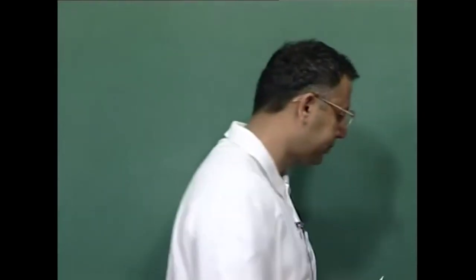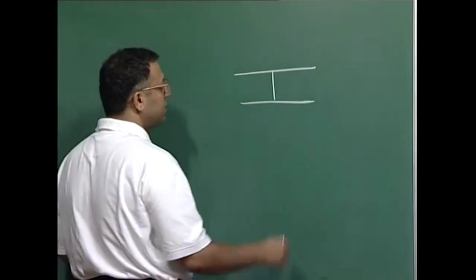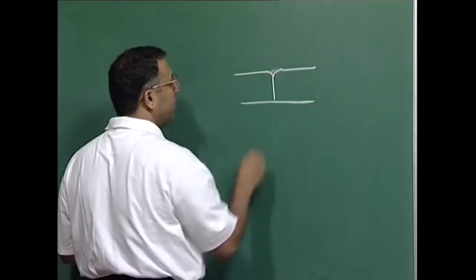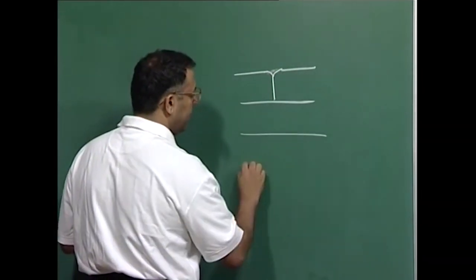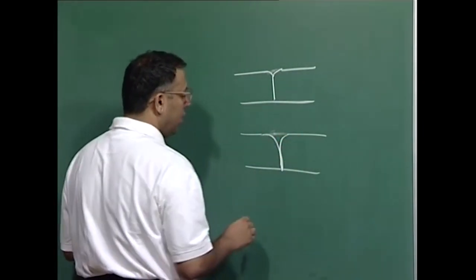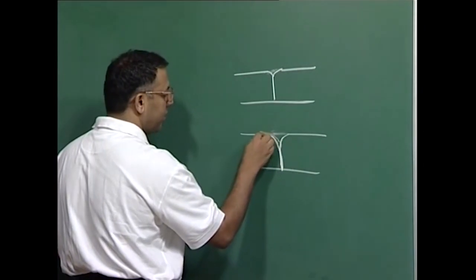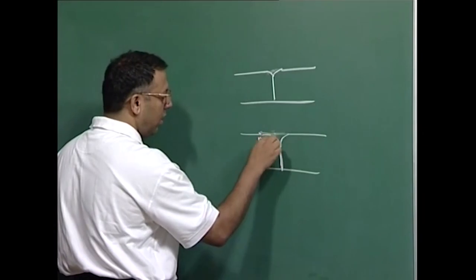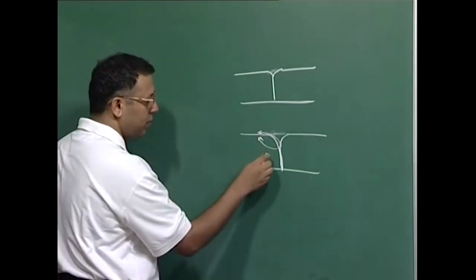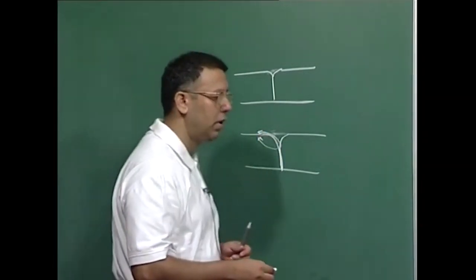A good example: suppose I have a polycrystalline material here with a vertical grain boundary. What will happen is that if I heat such a material, due to surface tension balance, a small groove would form and this groove will tend to deepen — purely an effect of temperature. For such a deepening to take place, mass transport has to occur from regions where there was material to the surface. It is observed that surface diffusion plays a dominant role in such problems because the diffusivity at the surface — due to the available freedom of atoms — is much higher than bulk diffusion.